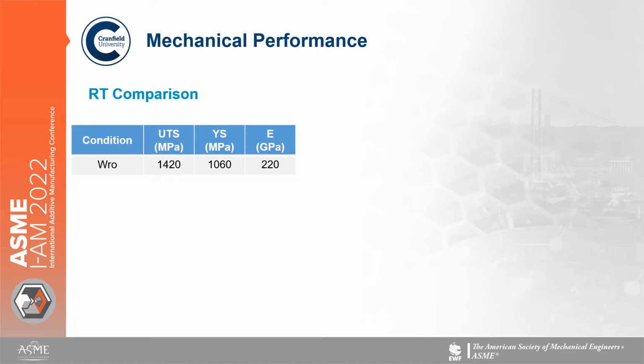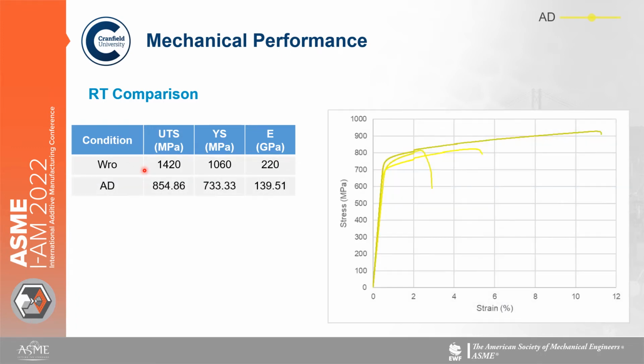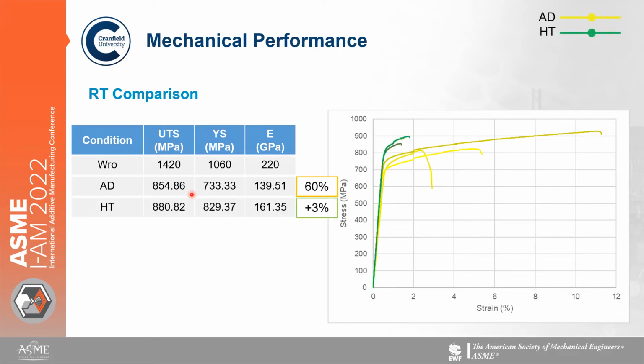So in terms of results, we compared the room temperature performance of Rene 41 in its various conditions. To start with, we have the wrought data from literature, which gives you a good indication of what Rene 41 is capable of in its wrought condition. Then we have our as deposited material from a previous study. So we see UTS is roughly 60% of the wrought material. When this as deposited material is heat treated, we get a 3% increase in the UTS, which is these green lines on the graph.